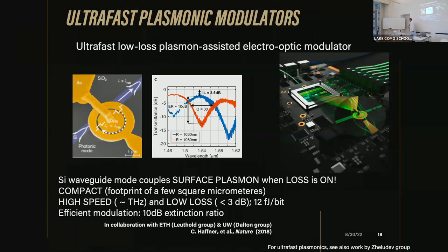Speaking of plasmonics, this early work we did with Jörg Leuthold from ETH Zurich demonstrates the key thing we are after in the case of plasmonics: speed. What we use here is a gold ring resonator, and this ring is filled with organic optoelectronic material, which changes its refractive index when you apply voltage. If you send the signal from this silicon waveguide, and the frequency of this mode doesn't match the frequency of this plasmonic resonator, then the signal goes through without any loss or coupling. If, however, you apply voltage and change the refractive index, now the frequency of this ring resonator mode matches the frequency of this waveguide, there is strong coupling, and light doesn't go through. So it's clear it works as a modulator.